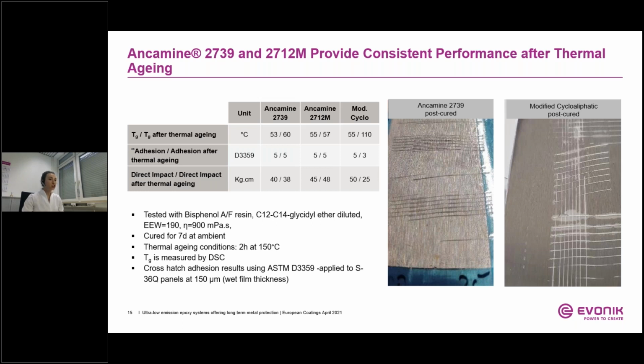In all cases, the Tg of the first set was around 55 degrees, whereas the second set exhibited a significant increase in Tg in the case of cycloaliphatic amines. So you can see cycloaliphatic amines have, after the post-cure, a Tg of 110 degrees. Also, the crosshatch adhesion and direct impact test of the cycloaliphatic amine were negatively impacted by the additional heating in the second set. Here, the crosshatch test is rated 5 for the first set, whereas the second set got a 3 as a rating.